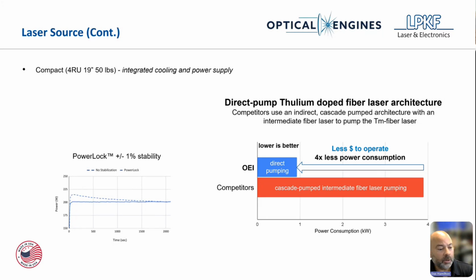It's compact, 4 rack units, it's a 19-inch rack mount, 4 units high. So it's about 6 or so inches high. And it's integrated again with the power supply, the driver, the software, the cooling. They have a feature called power lock, and it basically holds the laser power to plus or minus 1% stability, which is very important. We've found that in certain materials.